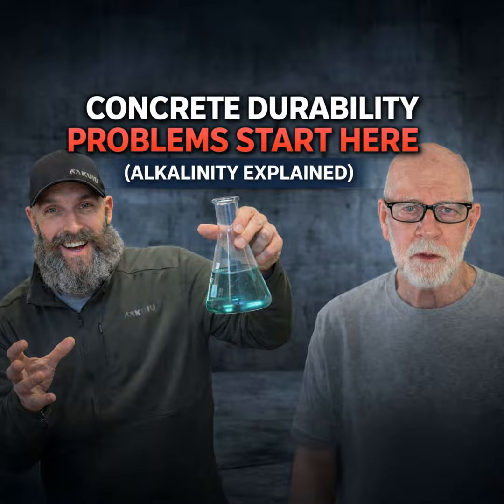It says the moisture migrates to the surface of the concrete because of the heat. Well, no, it doesn't work that way. If it's migrating towards the surface, that means it's containing a chemical that's activated by heat. That's not the water moving. It's something else that's moving. Because they said it's moisture, the moisture is moving through. I said, no, it's not. That's called diffusion. If something's dirty and there's a place that's clean, it wants to go from dirty to clean. That's the way it works. It's really that simple. So when the salts get more active, when they're warm, they want to move towards the warm side, and they bring the water with them. It's not the water bringing them; they're bringing the water with them. So it's kind of a double whammy here.